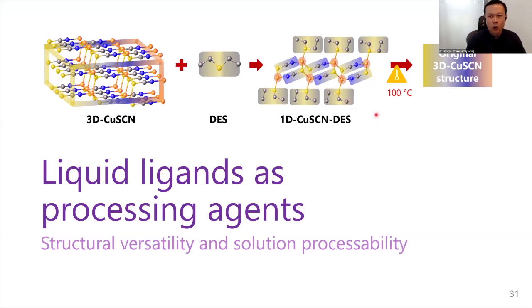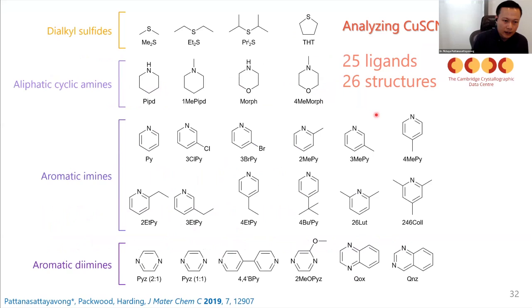And this is sort of the core concept that we are developing right now - basically, to process the metal and the primary ligands as original coordination polymers, then we add the second ligand that would weakly coordinate with the metal centers, but can later be removed more easily compared to the primary ligands. We can also see that all of these ligands can be co-ligands with CuSCN, copper thiocyanate, resulting in many beautiful structures like 0D, 1D, 2D.